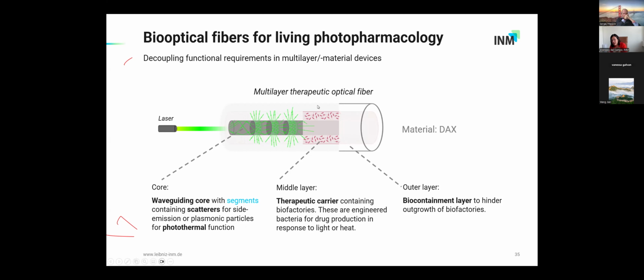In the intermediate layers, we have the biofactories, which are sensitive to light. So with these devices, we can bring light, we can outcouple light and excite locally also the factories in the intermediate layer. And we have an outer layer, which is the biocontainment layer to hinder the outgrowth of biofactories.